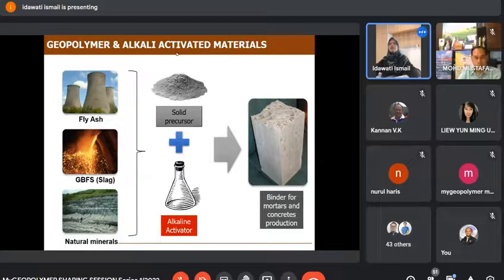So in general, it is using waste materials like fly ash, or GGBS or slag, or we can also use some natural minerals. Some of these waste or byproducts from the industry have certain properties. They have been used, for example, fly ash has been used not only with cement. So we call it supplementary materials or mineral admixtures. But in our binder, geopolymer or alkali activated materials, we use it solely. We don't mix it with any cement.